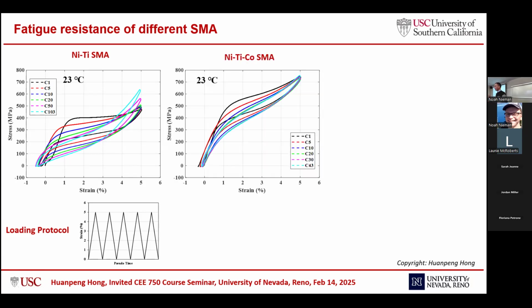So this is what the nickel titanium cobalt alloy behaves like. The yield stress is much higher, and the degradation is almost comparable to the nickel titanium alloy. This material fractures at around 43 cycles, indicating that it might have a lower fracture toughness, but we haven't tested it yet, just a speculation.